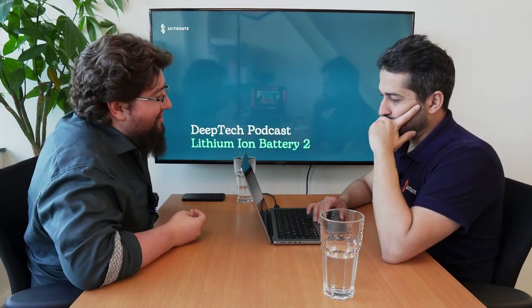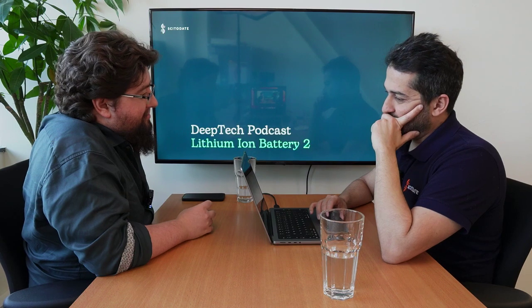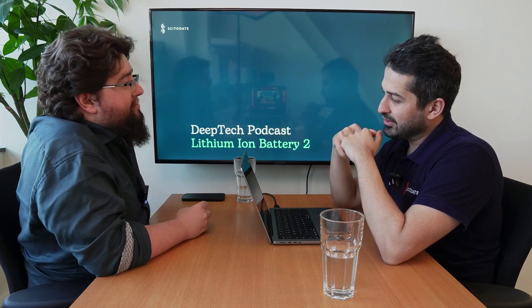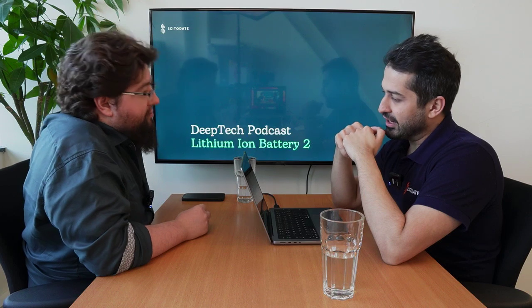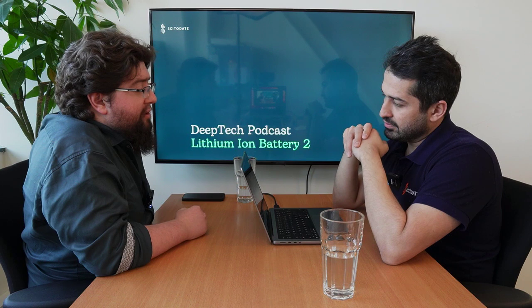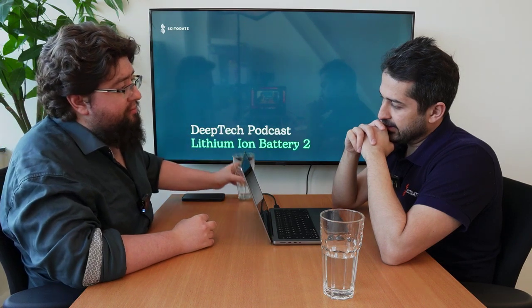Okay, that's very interesting. And the other one is doping. Essentially, they put in aluminum, magnesium, titanium. They dope it into the structure to create stability. So what does that accomplish? Does it mean that the cobalt is held tighter, or that when you take lithium in and out, the crystal structure stays stable? I guess it's a combination. To be honest, I don't know. I think here it is partially the structural stability.